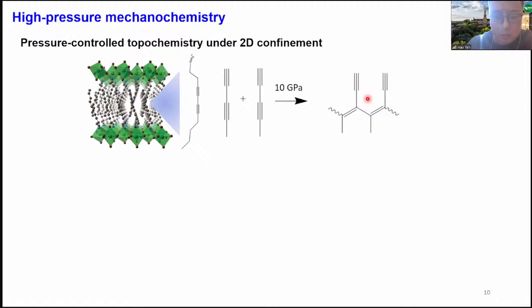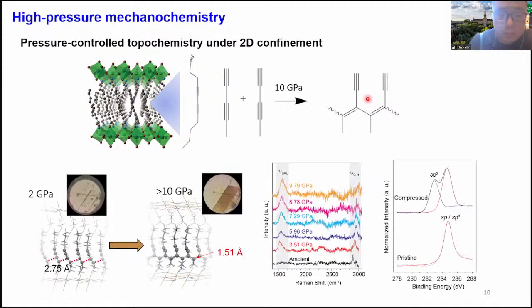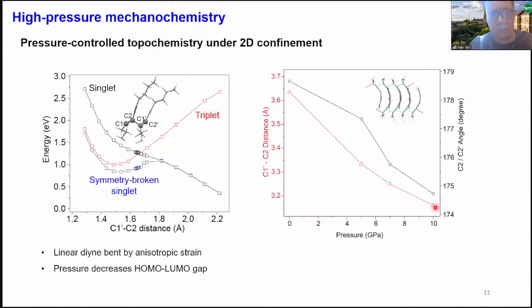So this is what we expect, and this is what we see in experiments. We can put a single crystal of this 2D perovskite in the diamond anvil cell, compress it. We can see the color change, but also in situ Raman spectroscopy shows the rise of a new band at 1600 that corresponds to the stretching of the CC double bond. Now, once this polymer is formed, it is metastable. We can release the pressure, recover the material, and you can actually see that the content of sp2 carbon rises due to this pressure. Now, there are two things that's particularly interesting to us about this reaction.